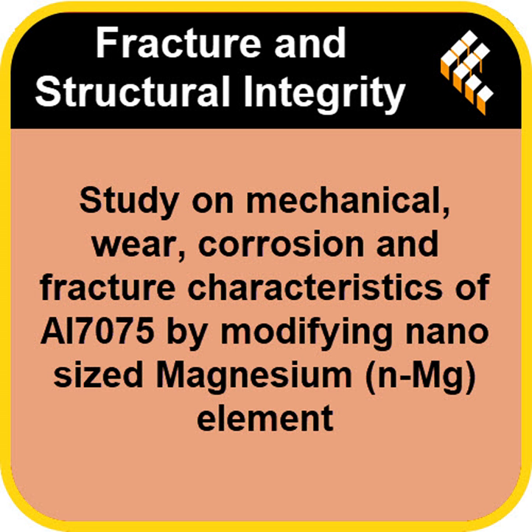Sure. If the anodic behavior is the overall problem, microgalvanic activity is the localized mechanism. You have these tiny, isolated electrical differences, like little self-destructing battery cells, between the aluminum matrix and those rigid Al3Mg2 phases we talked about earlier. The same ones that gave it strength. The very same ones. These micro-interactions accelerate the breakdown of that protective layer, and that's what creates those deep pits and cracks you see on the surface.